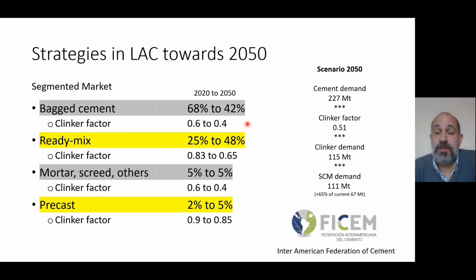So this segmentation of the market would allow us to achieve even lower clinker factors for the whole industry, and also the reduction in the proportion in which bag cement is used. As I mentioned earlier, it's a rather inefficient use of cement, and it can also contribute additional carbon savings. So the scenario for 2050 is that cement demand in the region will be 227 million tons, and with an overall clinker factor of 0.51, this means we will need 115 million tons of clinker being produced and 111 million tons of SCMs being used. And this represents a 65% increase in comparison with the current consumption of SCMs of 67 million tons.